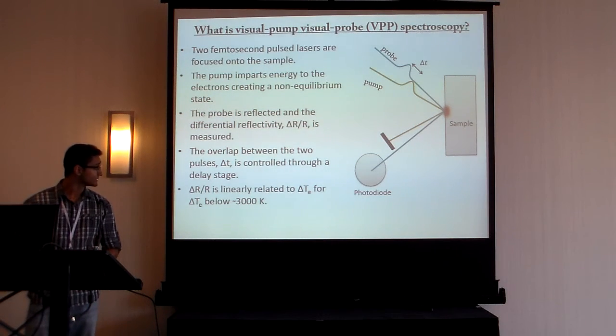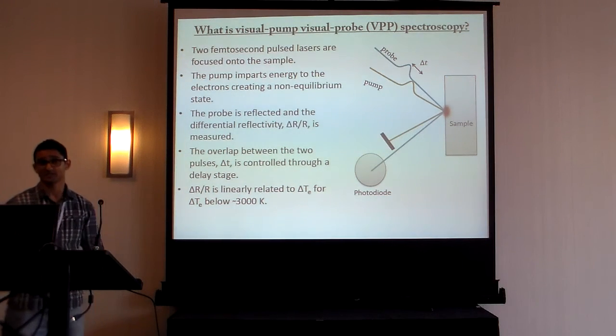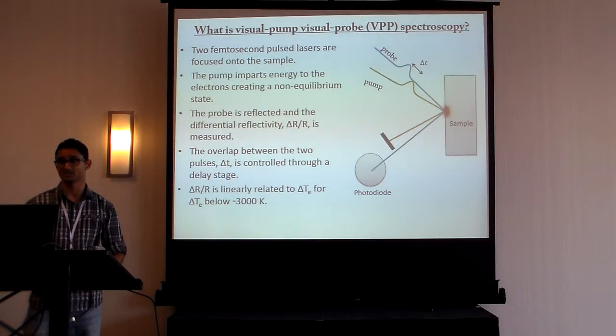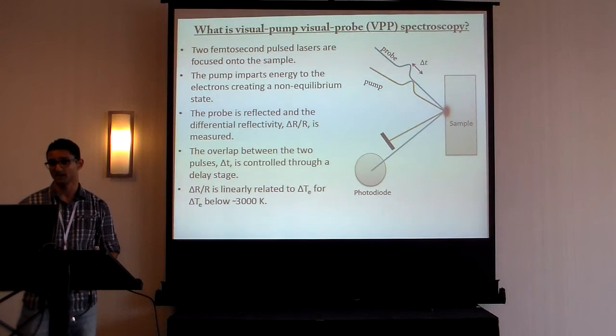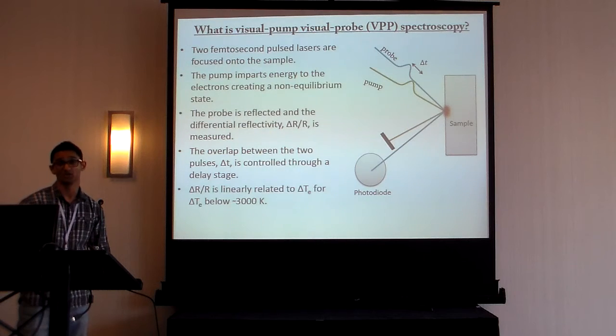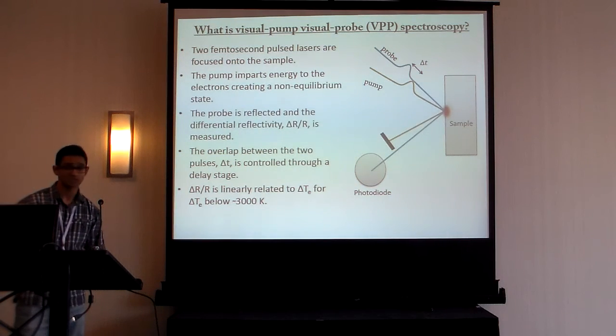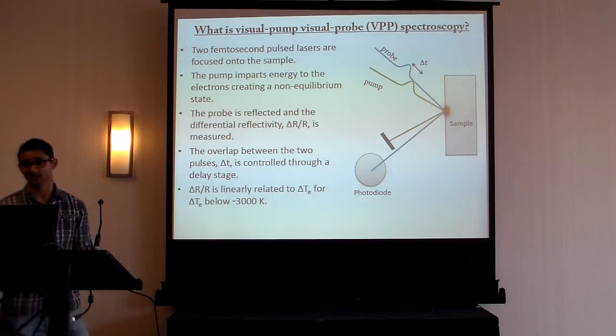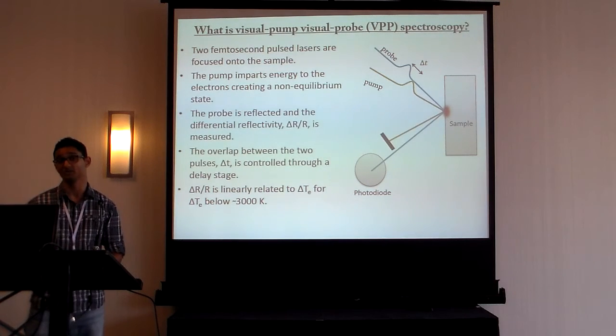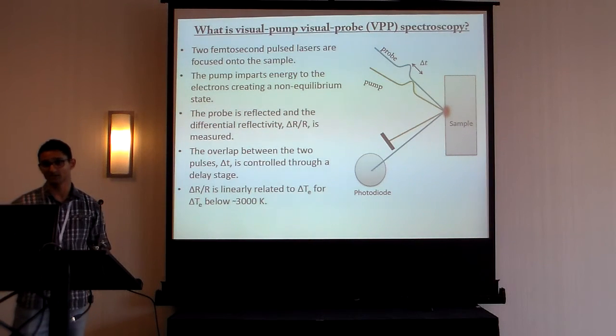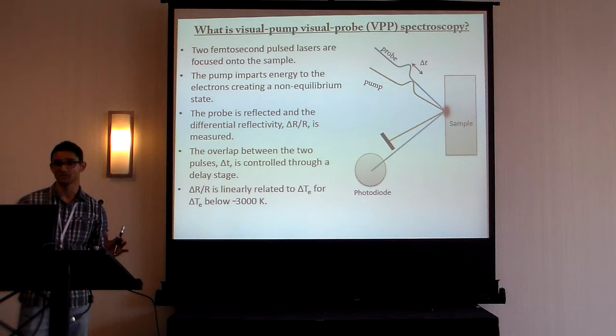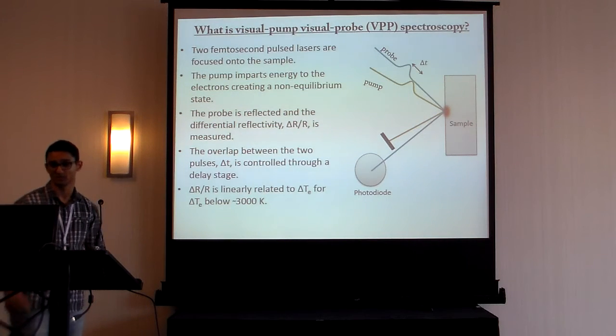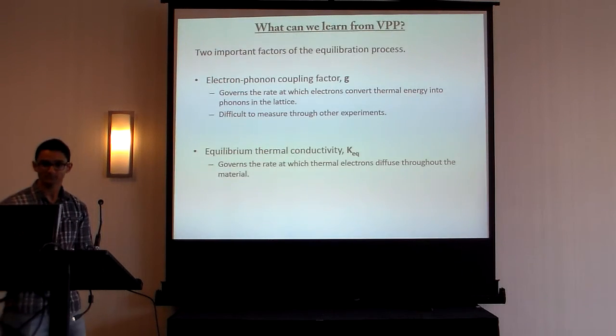The differential reflectivity signal is linearly related to the change in electron temperature for electron temperatures below 3,000 degrees Kelvin. So what we can do is parse over the time domain of the equilibration process by adjusting the relative overlap of the two pulses with respect to an automated delay stage.